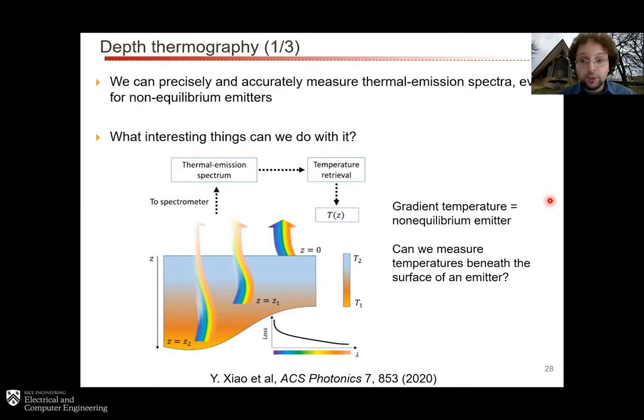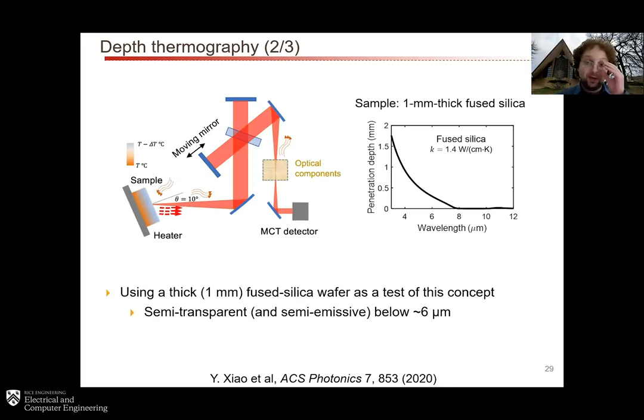Okay, so this is the basic concept of depth thermography: trying to retrieve the temperature based on the thermal emission spectrum that you measure. So let me show you how that works. This is one of these references that we use all of the time in our lab, fused silica. Fused silica turned out to be a really good test sample for depth thermography, because it's semi-transparent in the mid-infrared. Here's the penetration depth versus wavelength for our fused silica wafer.